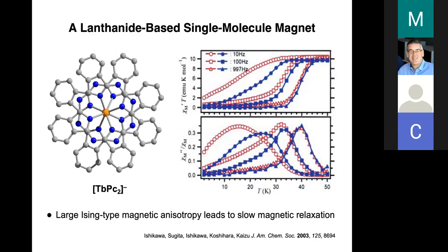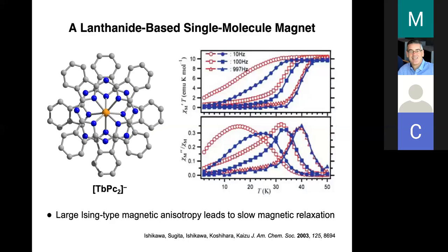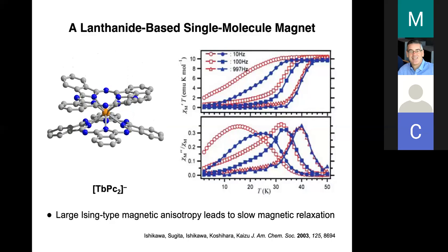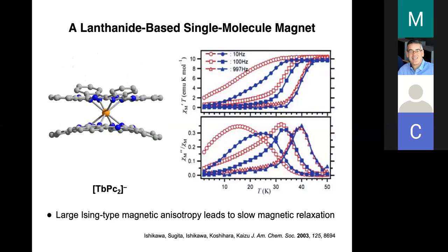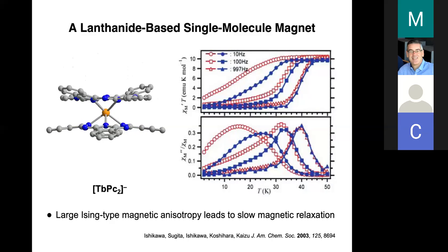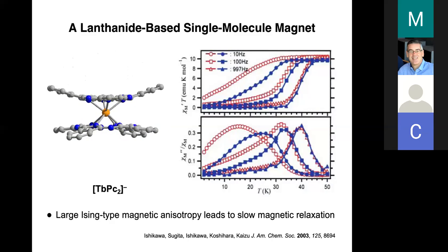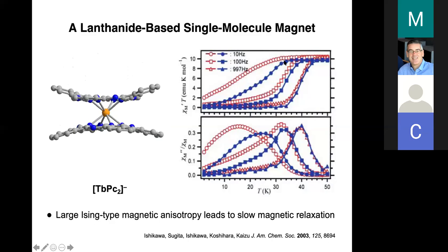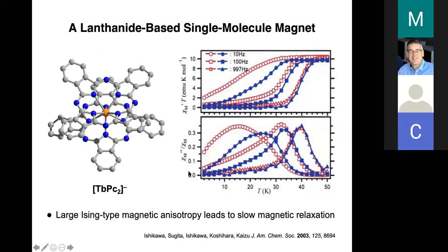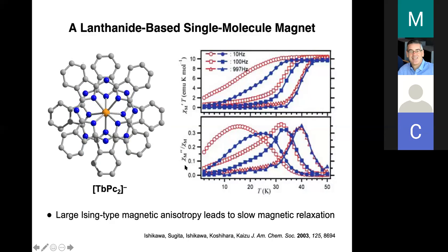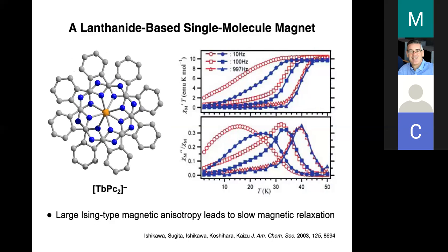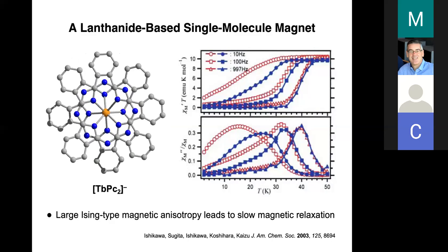That is, the magnetic moment, if it has a barrier to relaxation where it's only slowly relaxing, can't keep up with how fast you're switching the direction of the magnetic field. And so, don't worry about understanding the details of these plots of AC susceptibility, but this provides a way of directly measuring the relaxation barrier for the moment in one of these complexes.